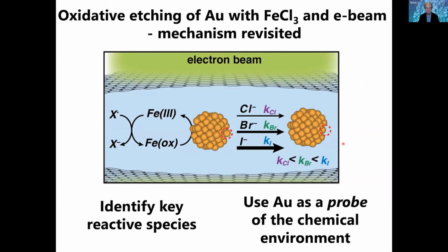Now, I mentioned to you that we had been studying these kinds of systems for a very long time. And in the course of all those studies, what we have been looking at is how various iron species are involved in etching the gold. That's a classic system. We've published papers for several years on it. I won't review them right now, but suffice it to say that if we add iron chloride or iron bromide or iron iodide to a solution that contains gold nanoparticles in the liquid cell, and we might have, for example, these two graphene layers and an electron beam passes through there, then, based on what I just showed you with the redox couples, we would like to know a little bit about what is the chemistry that goes on inside here.